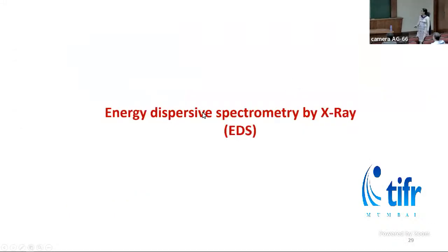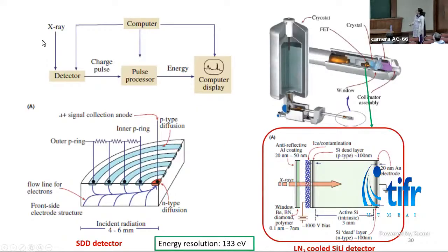Energy dispersive spectrometers are used to find elements present in the sample and also the composition of the sample. When an X-ray photon hits the detector, which can either be a silicon lithium detector or an SDD, that is silicon drift detector, it creates a charge pulse which is proportional to the energy of the X-ray. This pulse is processed by the pulse processor, digitized and kept in that particular channel. So it has a multi-channel analyzer. These detectors are being outdated now. These are liquid nitrogen cooled detectors. Here, this Si(Li) detector works as a reverse biased PIN diode.